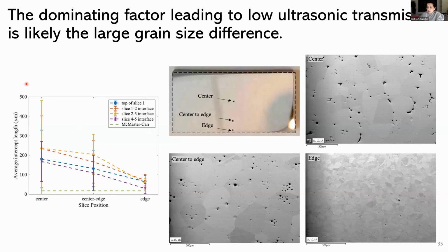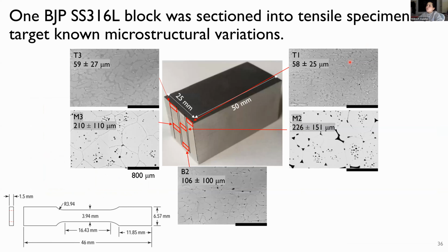The other thing that we noticed that we thought was interesting was that in the center to edge region, the pore structure that we were seeing in the samples was round and isolated. But once you got to the very center of the sample, and we could only look at this in the 2D plane, at least for now, what we saw was that the pores were pretty irregularly shaped. And this got us wondering how these pores would be represented if you were to look at them in a three-dimensional space.